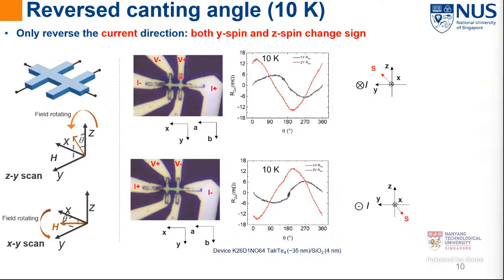Then for a double check, we do another experiment. In this case, we keep the sample direction the same, but change the current flow direction. For example, firstly, we flow current from the right to the left side. Then now we are flowing current from the left to the right side. In this case, from the conventional spin Hall effect, and also the spin momentum locking, the Y spin should change its sign, and the new thing from our material is that when we change the current direction, the Z spin should also change its sign, and as a result, the total spin direction should change by 180 degrees. We can also read this from the figure. The high resistance case shifted by 180 degrees. The experimental result is consistent with our theoretical prediction.